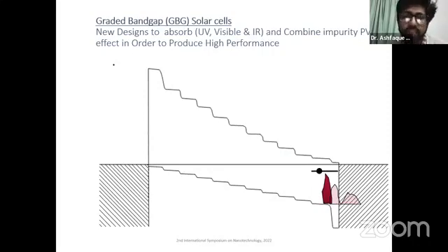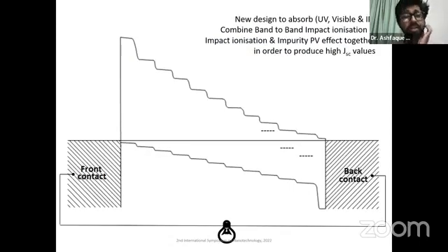That means if there is a low energy photon absorbed, it can actually elevate an electron to a defect level inside the material, and that defect level can actually hold the electron, and another photon absorbed can actually elevate it to the conduction band, and therefore it can actually give birth to multiple exciton generation instead of just one exciton per photon.